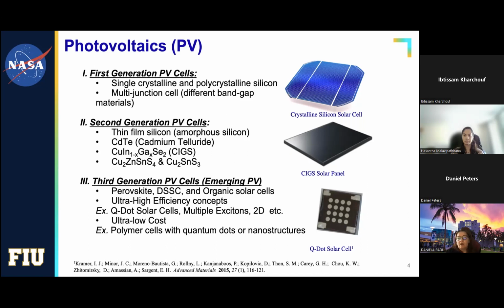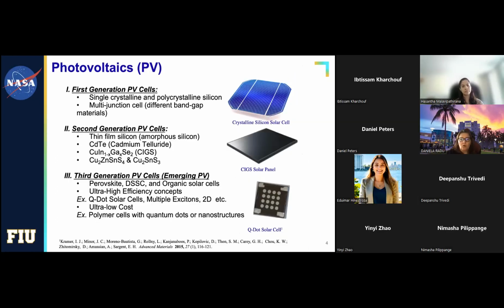Well, nanotechnology came to the rescue, and more than 1.5 decades ago, people started to elaborate these materials at the nanoscale. So we learned how to make nanoparticles from cadmium telluride, from copper indium gallium selenide, from the other chalcogenides listed here, copper zinc tin sulfide and copper tin sulfide, and even from amorphous silicon. I want to point out that I will have most of my presentation about the nanoparticles and nanotechnology as applied for Gen 2. But I just want to point out real quick the fact that there are these emerging PV technologies.